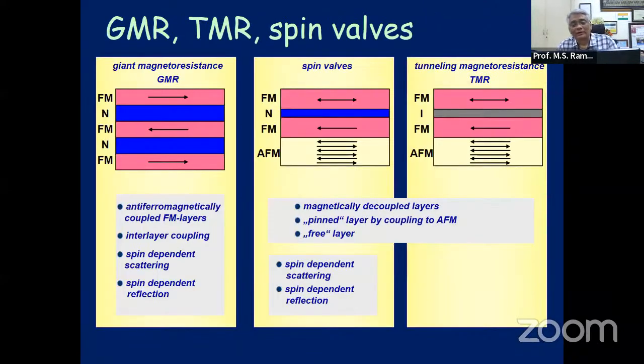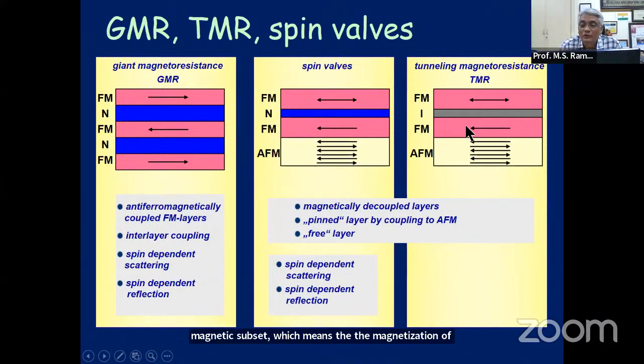This has led to a great activity in the last 3-4 decades. You have GMR, giant magnetoresistance, tunnel magnetoresistance, and the concept of spin valves, where you see that I can deposit a ferromagnetic layer on an antiferromagnetic substrate, which means the magnetization on this layer can be completely pinned, so you don't let it move around.